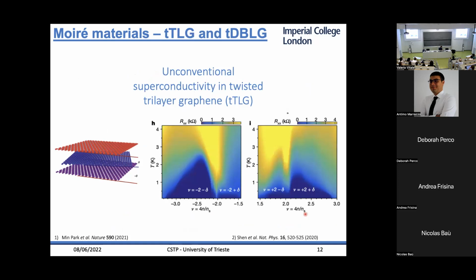A second example that came a few years after that is the same group from MIT managed to build a device with twisted trilayer graphene, and also in twisted trilayer graphene, the same thing happens basically. So you have a superconducting dome for a specific value of the filling and insulating states. Although the superconducting states in twisted trilayer graphene are thought to be quite different from twisted bilayer graphene. It's more robust, and it's probably a spin triplet. It's called a spin triplet superconductor.